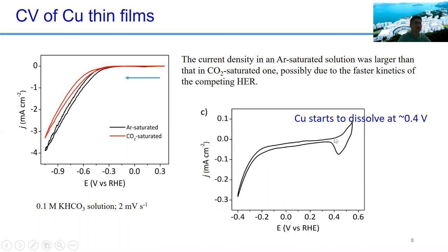We can also see that the copper actually started to dissolve at the high potential end going forward. So we need to make sure that the voltage will be lower than 0.4 volt.